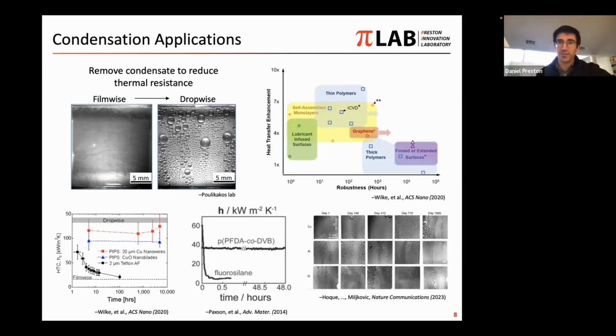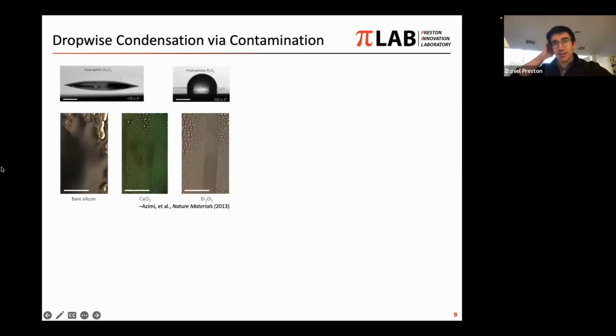And so a lot of good progress in trying to improve condensation to longer time periods and avoid this degradation of the surface chemistry that transitions us back to film-wise. And in fact, a lot of cool work lately has been focused on getting dropwise condensation almost naturally or spontaneously via contamination. And so I refer back here to a decade ago when a paper came out in Nature Materials on rare earth oxides, suggesting that these might be a good candidate to promote dropwise condensation. And we have some images from their paper here showing condensation on the surfaces of two of these rare earth oxides, nice dropwise mode compared to bare silicon.